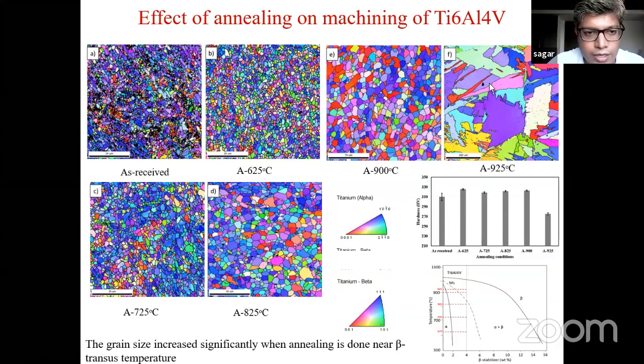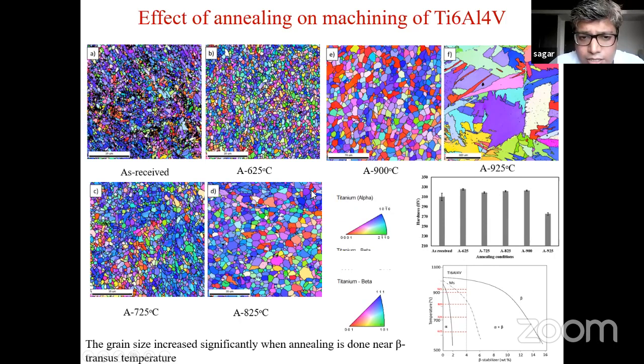Whereas here, in this annealed condition, the depth of cut is far more than the average grain size. So that's why grain size has no effect while machining this lower grain size sample. But when your depth of cut is comparable with the grain size, yes, it will have an effect.